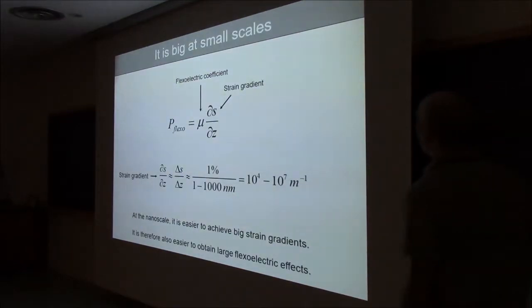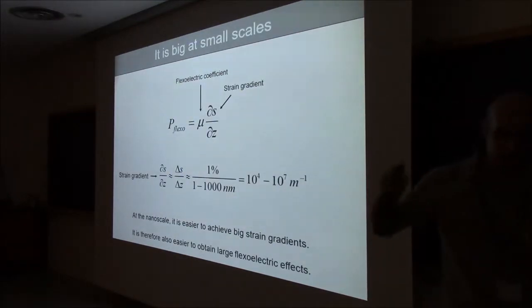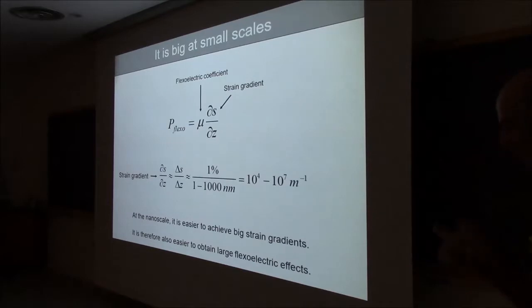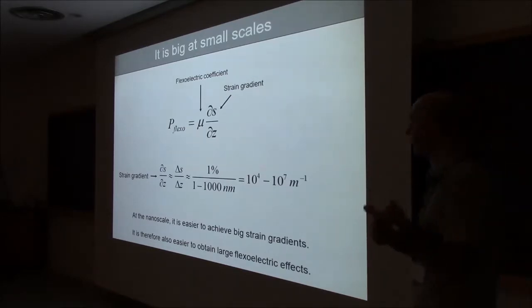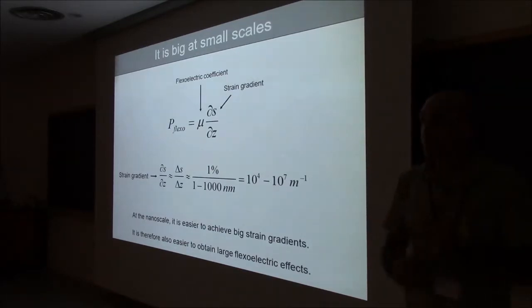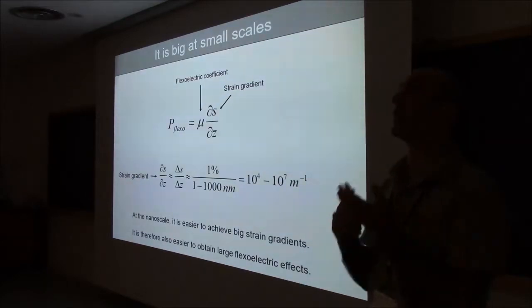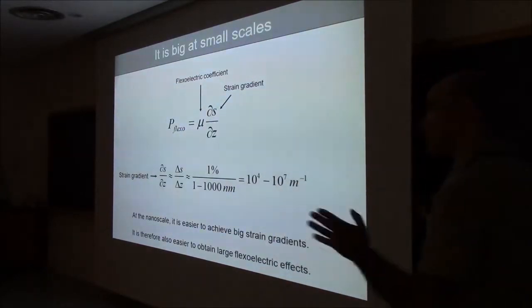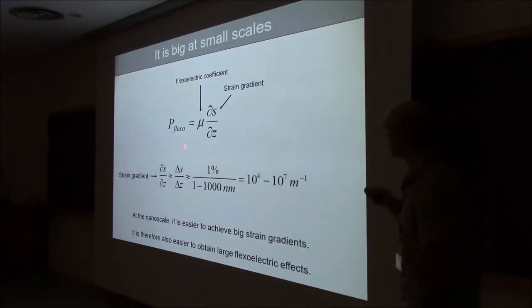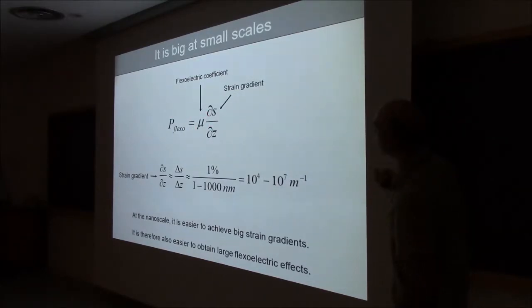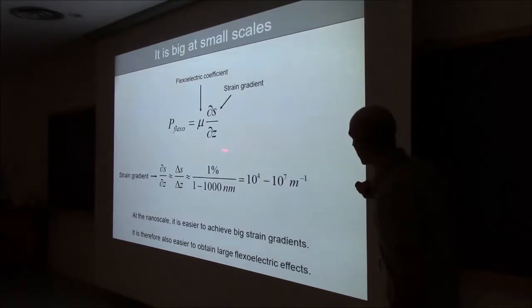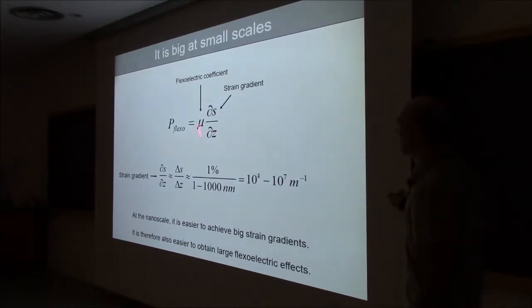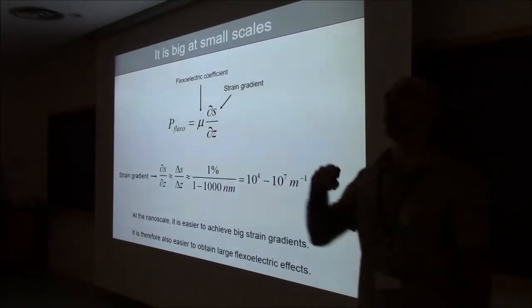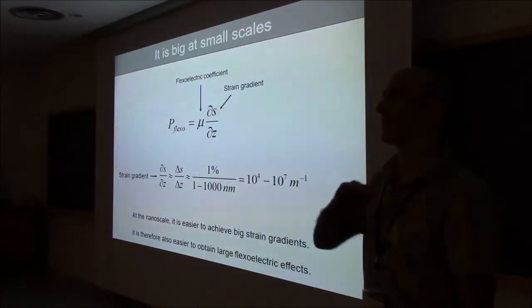Okay, so the two features so far: it's proportional to the dielectric constant and it's very universal. And the third very important feature is that it's inversely proportional to size. I need to explain this a little bit better. The flexoelectric polarization is the flexoelectric coefficient times the strain gradient. Now, the flexoelectric coefficient more or less is size independent. It's a constant. Should be a constant.